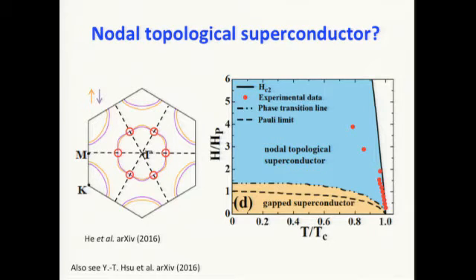Okay, any last question? Yeah, for the mixture of singlet and triplet pairing in the presence of the field, what portion of the Fermi surface is mostly singlet and what portion mostly triplet? Yeah, for the picture I've been talking about, most relevant are K and K prime because they have the largest spin-orbit coupling. You can see the spin-orbit splitting is more significant at the K prime pockets than the gamma pockets. So if you didn't have the gamma pocket, would you have a majority of triplet pairing, or would you still not? We still don't have a majority triplet pairing.